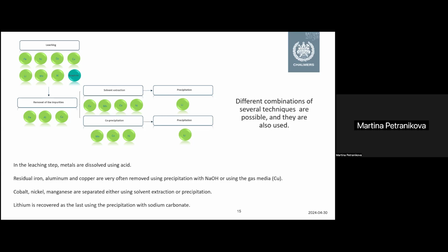If the mechanical pretreatment is effective, then usually these are at a very low concentration, but we still have to remove them before we are going to process transition metals. And very often what is used is either solvent extraction, the process I will talk about later a little bit, or co-precipitation. And then lithium is usually recovered as the last one. There is also now an approach where transition metals are recovered before the impurities.